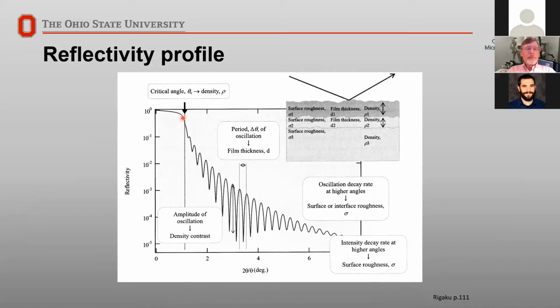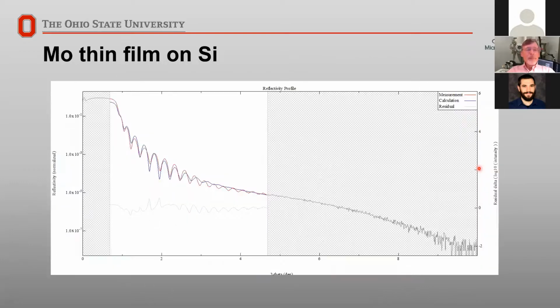The size of the oscillations tells us the change in density. And the way that this curve drops down and the way these oscillations die out give us information about the roughness of the layers. So we have to start with a model, and then we modify the model to match our experimental data. So here is one model that we matched to a molybdenum thin film grown on silicon.